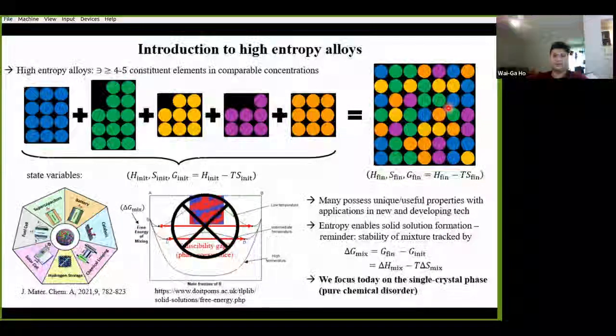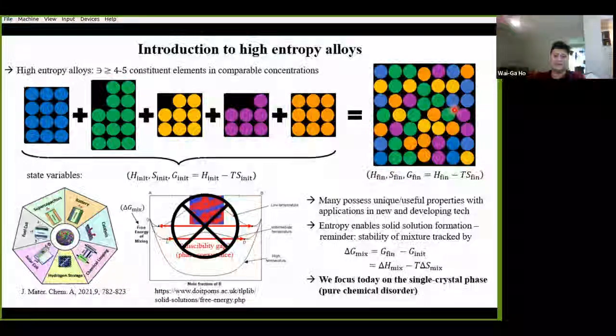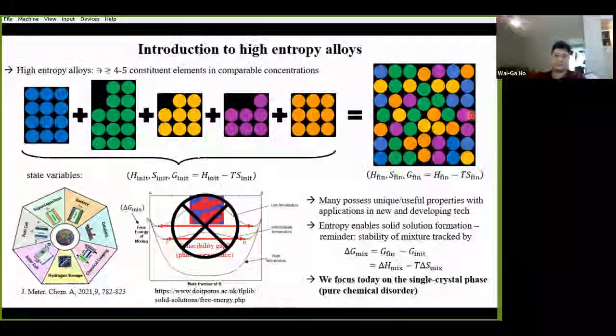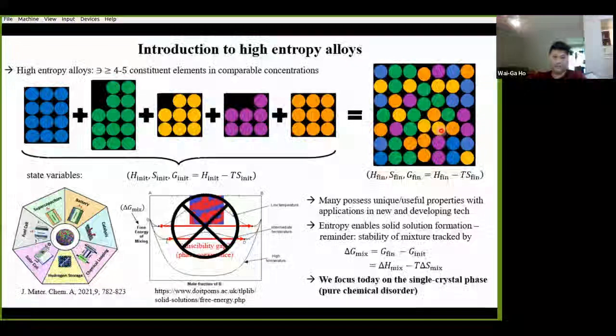Also, if anyone's wondering, wait, what about structural disorder? Well, this also warrants some attention. However, if I take the chemically disordered lattice that I have over here and then introduce a small vacancy like I did on the last slide, well, we already saw that this distortion is a pretty local perturbation on top of an already established crystal structure, which remains pretty square away from the vacancy, in this example at least. So what that means is, we should still try to understand the single crystal problem before we start perturbing it